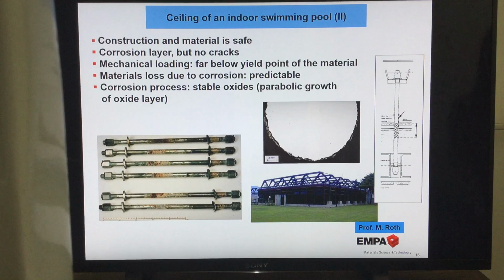We have seen the construction, the design. We were very low in the static stress of these steel hangers, very far away. The material selected showed some corrosion, a corrosion layer, but no cracks. And again, the mechanical loading is far below the yield point of the material. The material loss due to corrosion is predictable. And in the corrosion process, at the end, stable oxides are formed. You can make this also in a test. There is this so-called parabolic growth of the oxide layer.